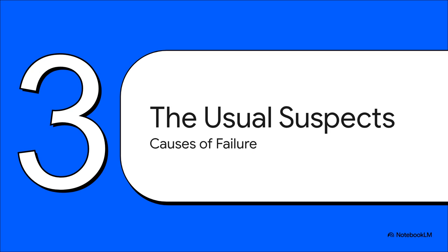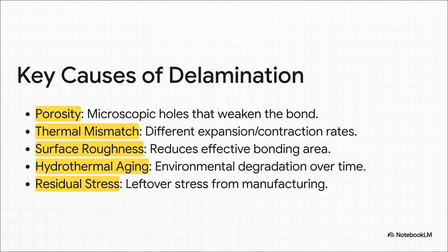Okay, now that we know how to investigate the crime scene, let's meet the culprits. These are the main reasons that adhesion gets weakened and delamination takes over. Here's our rogues gallery. First up, you've got porosity. Think of it like microscopic potholes that just create weak points all over the bond. Then there's thermal mismatch. This is a constant tug of war, where the coating and the surface expand and contract at different rates until they basically rip each other apart.